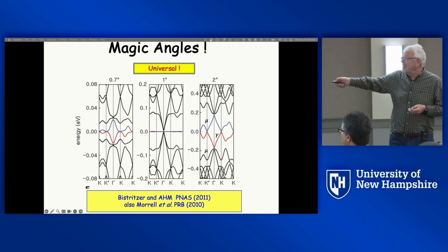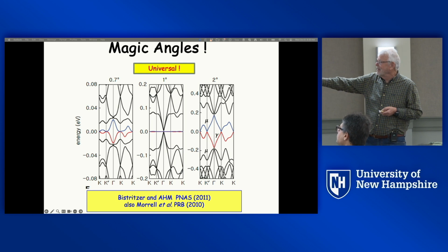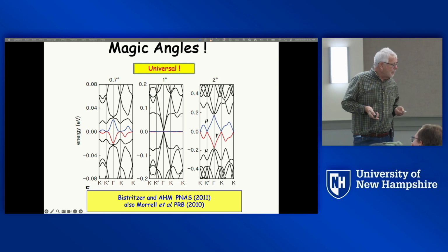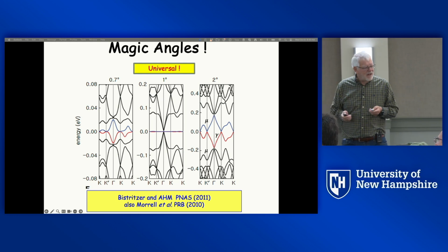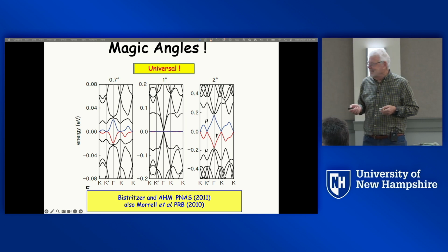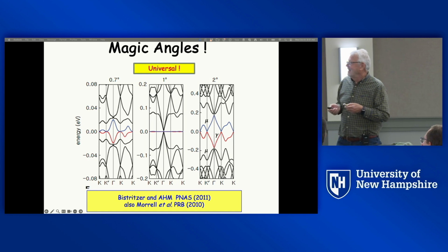So this is a narrow band. There are actually 8 states here for each momentum. And the velocity of each of these states is typically about a kilometer a second. Okay, so this is slow electrons, not slow light, but I think you can make light even slower, but this is slow electrons. In ideal models, you could make the electron velocity 0.